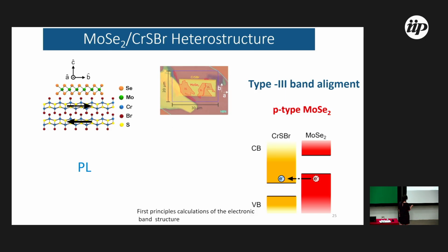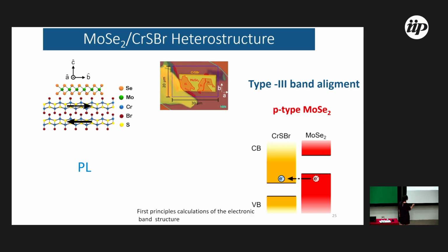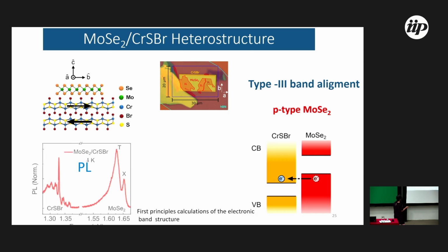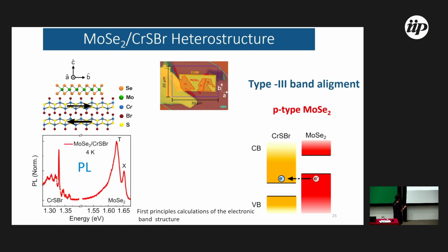So here is my flake of CrSBr, the crystal axis, and I put a few layers of MoSe2. If you measure the emission, this is the emission from MoSe2, which is very separate from the emission of CrSBr.